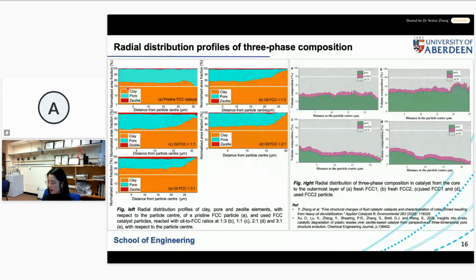For this FCC catalyst, we can segment the main structure of the catalyst, which is the clay, and also quite a lot of pores inside. That is the design feature of this FCC catalyst. Another component is the zeolite, which plays the catalysis role in this process. This figure tells you the distributions of these three segmented components for one of these FCC catalyst particles.